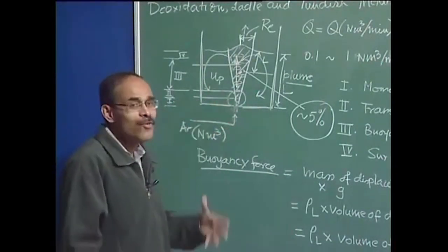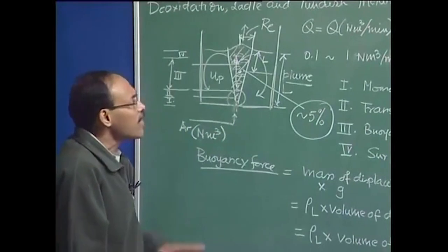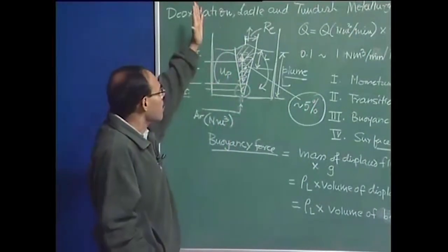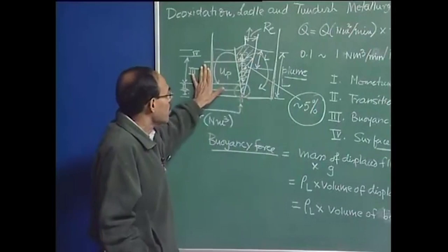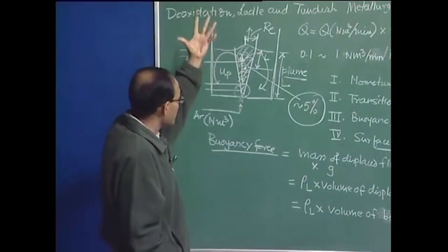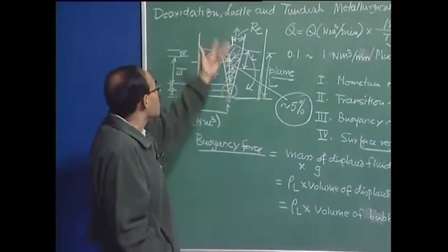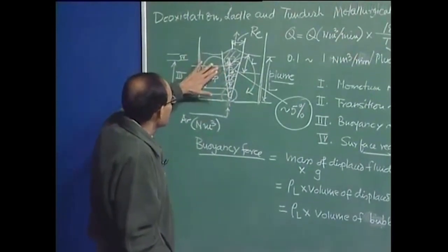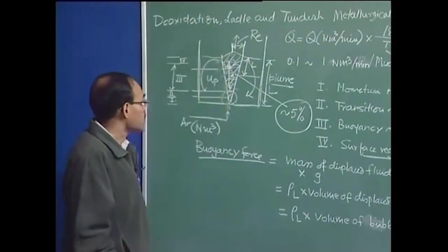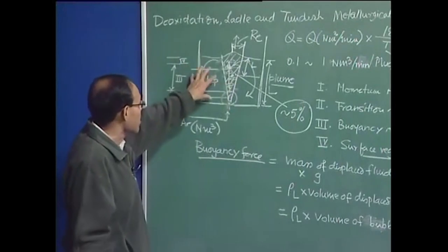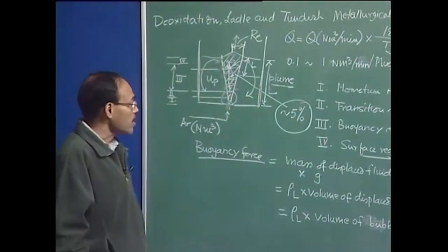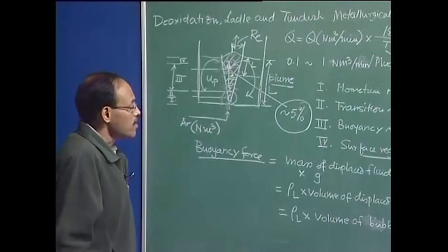Given this picture, we can conceptualize the gas injection phenomenon as like an unconfined jet, because the gas volume fraction is very small. It is rising through a very deep bath; the bubbles are far from the walls. It is as if there is an unconfined buoyant plume rising through the molten steel bath, and energy is continuously transferred across the plume boundaries to the molten steel. The bubbles give away their energy to the fluid, and the fluid keeps circulating, generating a strong convection current in the system.